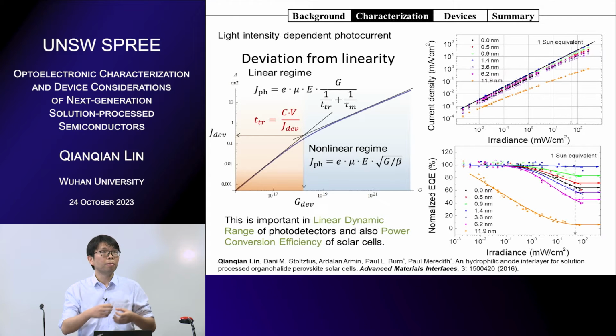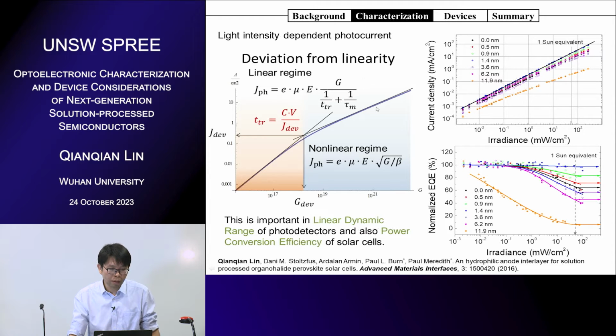If they can move very fast, then the recombination rate can be lower. So from the kink, we can also determine the carrier mobility of the semiconductor. I won't say more about this technique, but it does tell us something about charge transport, and we can determine the carrier mobility. And this is very easy to measure. We just need a steady-state CW laser, and we can tune the intensity and get photocurrent. We can easily extract the mobility, and we can also have a look at the charge recombination.